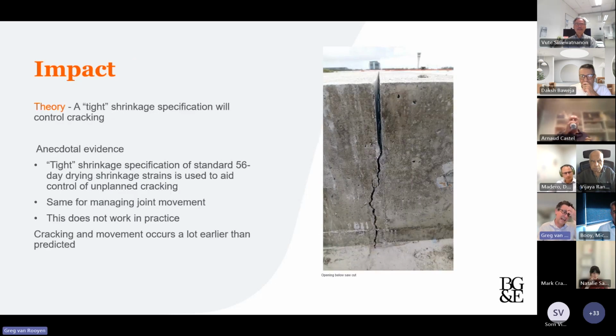So because of that, there's a tendency to want to put a tight shrinkage specification or requirement in a document to encourage, I guess, cracking to happen the way you want it. Great picture there: when you take a piece of unreinforced concrete and you give it a decent saw cut, the crack will happen in the cut. But this doesn't always really work in practice. It's quite common to see cracking happen in an unplanned way. And the movement clearly occurs a lot earlier than what we're thinking in the standard, and I'll show you a little bit of that in a little bit.